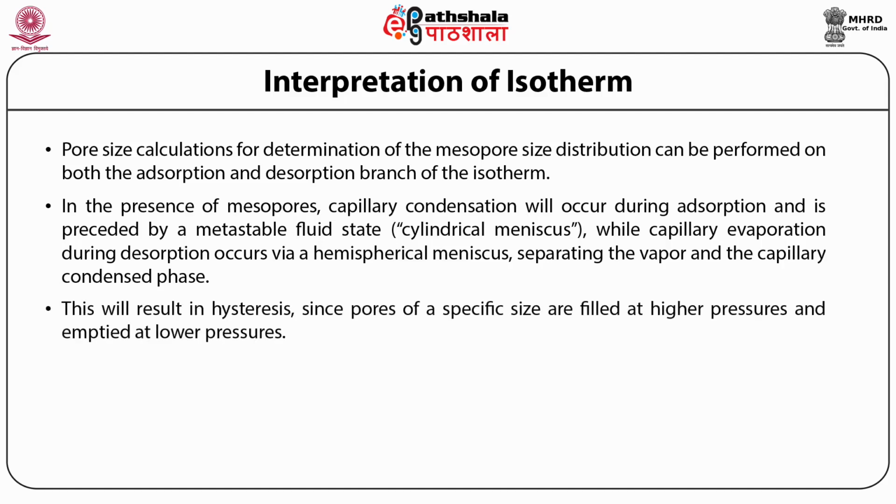This state is called cylindrical meniscus, while capillary evaporation during desorption occurs via a hemispherical meniscus, separating the vapor and the capillary condensed phase. This will result in hysteresis since pores of a specific size are filled at higher pressures and emptied at lower pressure. So they are filled at high pressure and emptied at a lower pressure.